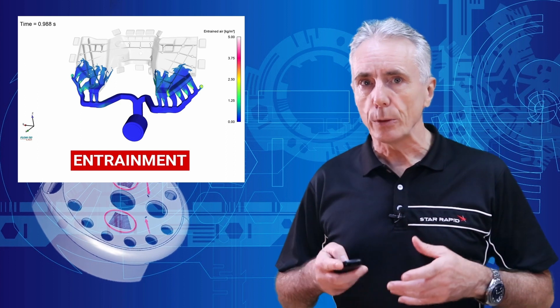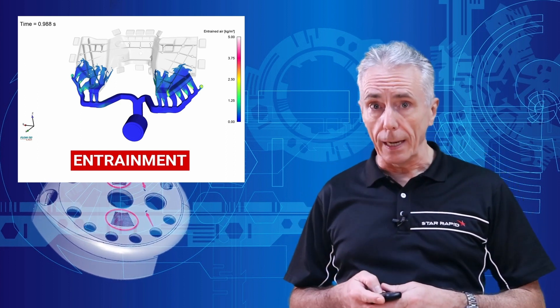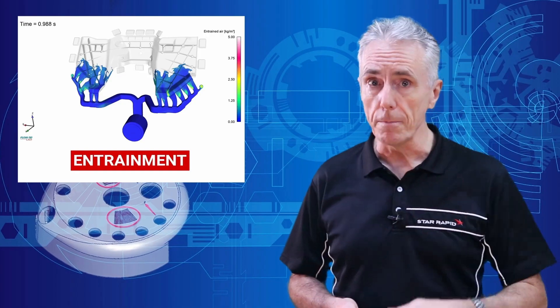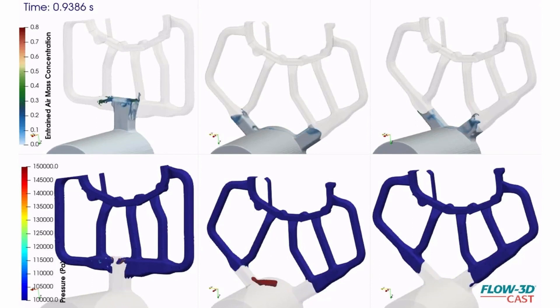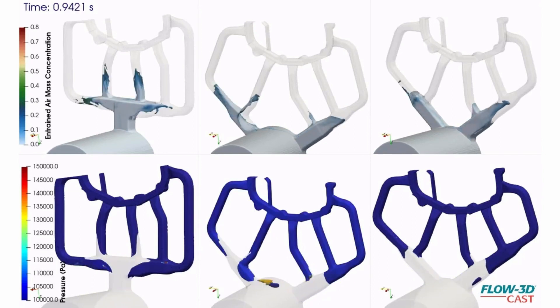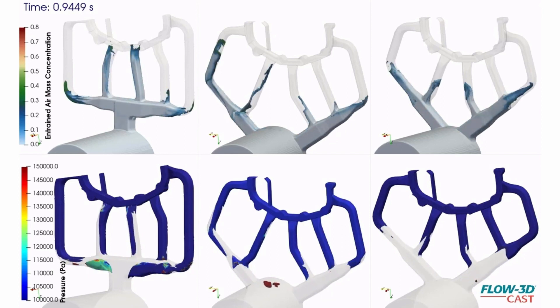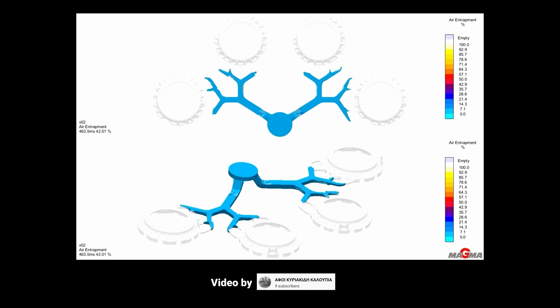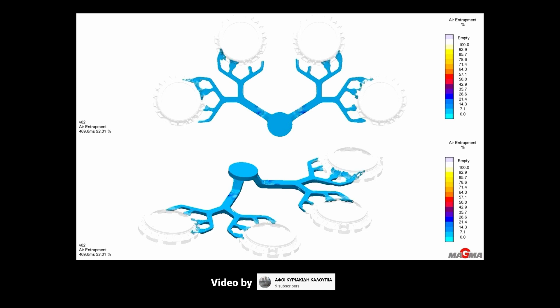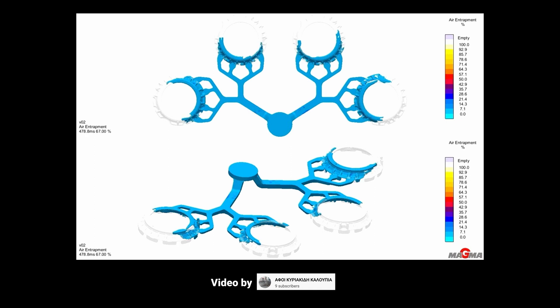The way to avoid this is to ensure that there are no obstructions in the die, as mentioned in our previous video. Another way is to ensure that you position the gate such that the material stands the best chance of flowing through the whole part without jetting over holes in the die or jetting perpendicular to heat exchanger fins, for example. If you work closely with your PDC supplier, they can run a simulation tool such as MagmaSoft, which is the PDC equivalent of mold flow for plastic injection molding. They can then tell you where you're going to have problems long before the design is fixed.